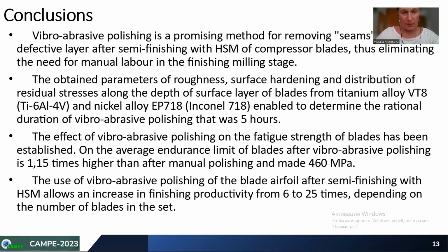The effect of vibro-abrasive polishing on the fatigue strength of blades has been established. On average, the endurance limit of blades after vibro-abrasive polishing is 1.15 times higher than after manual polishing and made 460 megapascal. The use of vibro-abrasive polishing of the blade airfoil after semi-finishing with HSM allows an increase in finishing productivity from 6 to 25 times, depending on the number of the blades in the set.